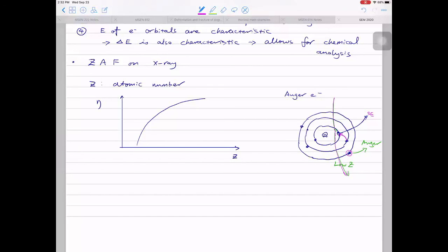The person who discovered and really understood this phenomenon is a French scientist called Auger. So this type of electron is named after him, called Auger electrons. There are a number of Auger electron microscopes in the United States, but not many. I think maybe not more than 10. That's my impression. It's very useful, but not very easy to use. Auger electrons are of such low energy that they are easily absorbed by the material. So you can only study the very, very surface of the specimen.